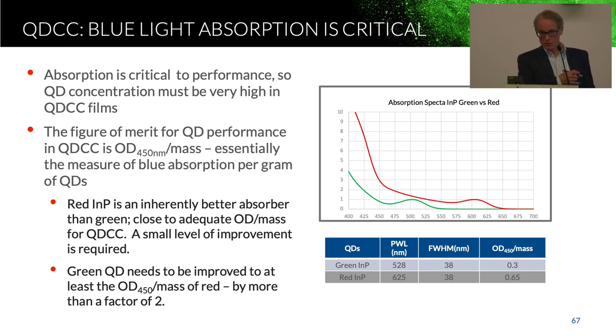So this is standard indium phosphide. These numbers can be improved incrementally. The red is not a problem. You can get it into the range where you need it pretty easily. Green is not going to be up there. So this is a limitation of this material.